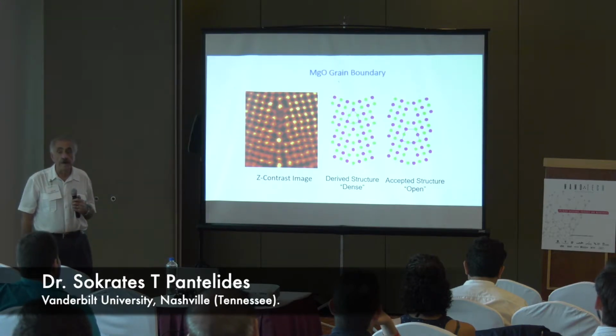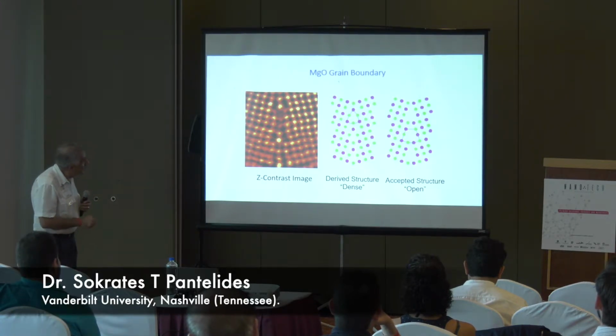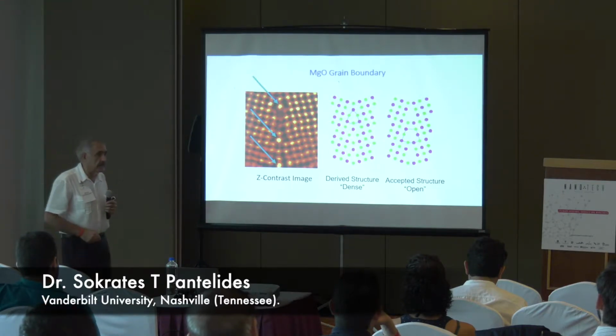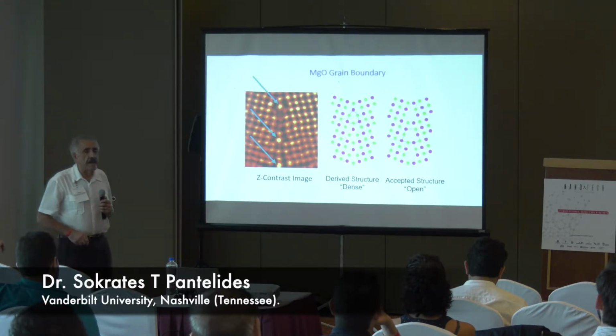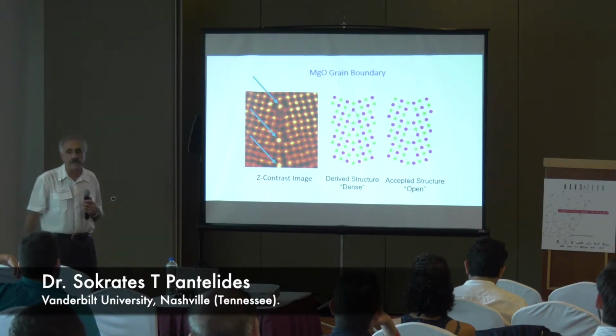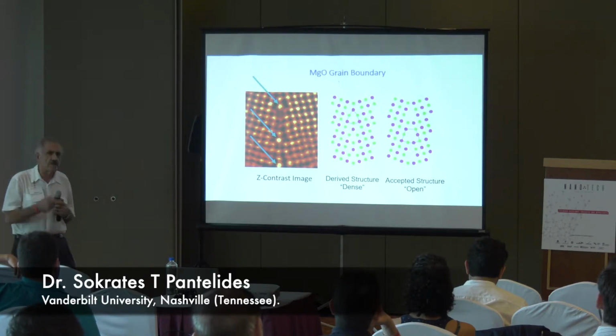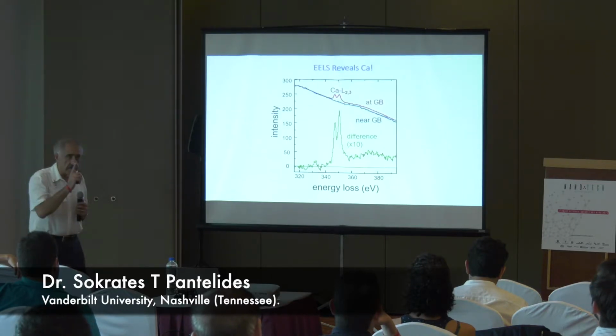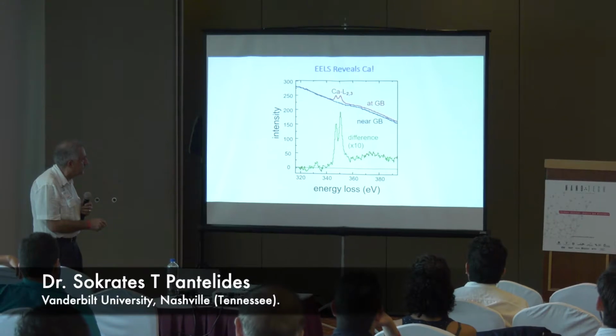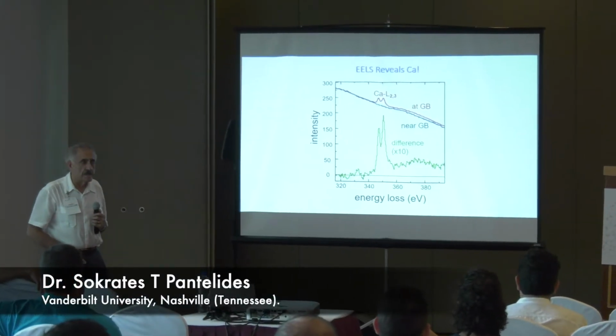So we said, what's going on? Well, if you look carefully, you see a few bright spots. Right? Those bright spots were the tells. We bought this bicrystal, and the place that sold it to us assured us that there are no impurities in there. But those bright spots with Z-contrast say something is there. Sure enough, with EELS, electron energy loss spectroscopy, we found a calcium edge, and this is the difference between these two curves. So we have calcium in there.